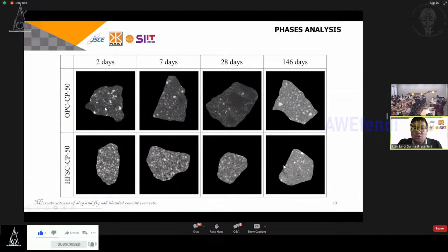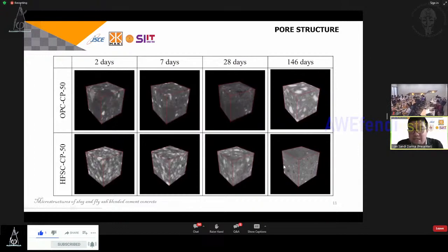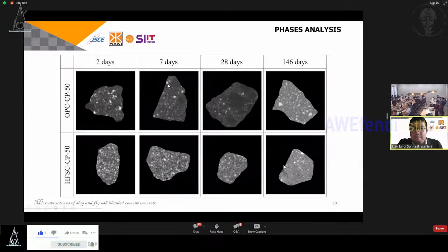And then in here, you can choose an ROI. What is ROI? ROI is a region of interest, the specific area you choose to evaluate. From the ROI, you create a new specimen, and then you will achieve a VOI, volume of interest. You can imagine in the VOI you will have several slices, and then you immerse them, and you will achieve a VOI here. You can see here the brighter things in the image show high density, and the darker shows the void.